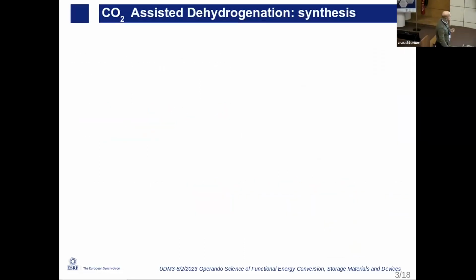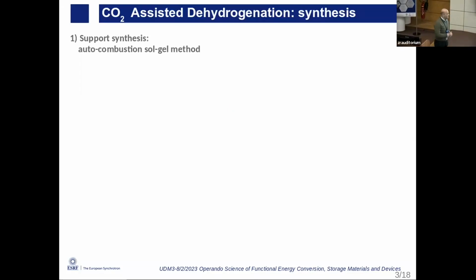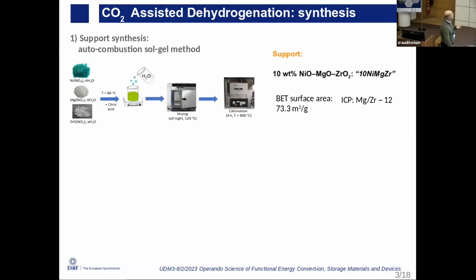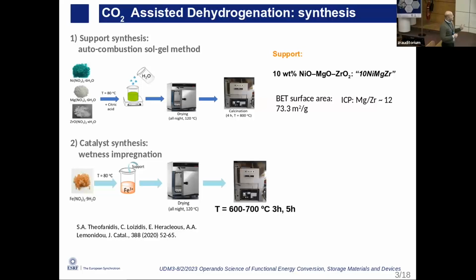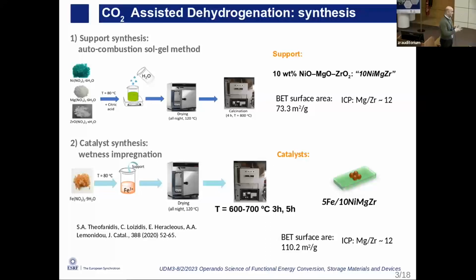And the idea that came up to our collaborators in the laboratory of petrochemical technology in Thessaloniki was to try to improve the production of this catalyst. And they did it by the sol-gel method, preparing a support with a reasonable area, mixing together nickel and magnesium oxide and zirconium to give thermal stability. And on top of this, they created a catalyst by impregnating with iron oxide. The aim of this part was to find the best compromise in the synthesis. So what is the best temperature and also the time that you need for this calcination. Accordingly, they found a good catalyst with this kind of percentage in terms of ratio of iron and nickel, and with a reasonable area as well.